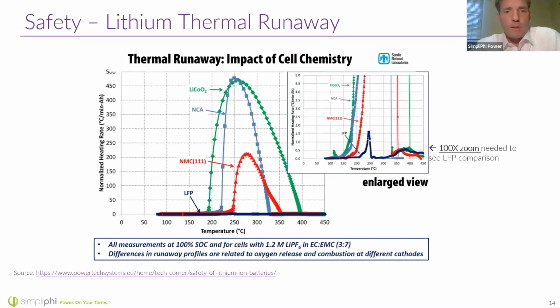So this graph is a little bit hard to understand. What you have on the vertical axis here is normalized heating rate. And what does that mean? It basically means the amount of heat that is released due to the battery. And the word normalized here means that we're dividing by the size of the battery, right? So we're looking at the degrees Celsius the temperature of the battery changes per minute. So how quickly does the cell heat up? And then we also want to divide by the amp hour.